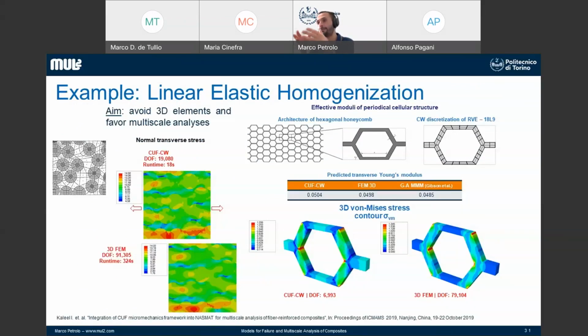So this is an example that should help you to understand better what I said. So basically, instead of considering the entire composite, we consider this volume here. So this square here is our RVE, in which you have a number of fibers and some matrix. So we consider this as a representative of the entire composite. And then we run static analysis on this kind of structure. And we get the stress field along this RVE, and then we transfer this stress field to the macro scale, as we will see soon.